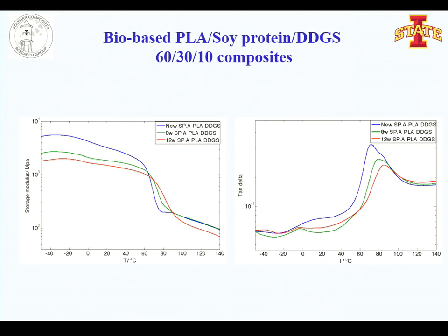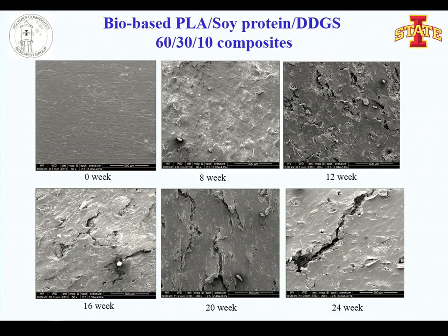We couldn't do any dynamic mechanical thermal analysis for the higher degradation rate because the material is very brittle after 24 weeks. But we measured at 0, 8 weeks, and 12 weeks, and we found that the elastic modulus decreased systematically, and the glass transition temperature shifted to higher temperature with increasing degradation. Again, this is probably due to the degradation of the amorphous part in the material, and the remainder has high crystallinity.